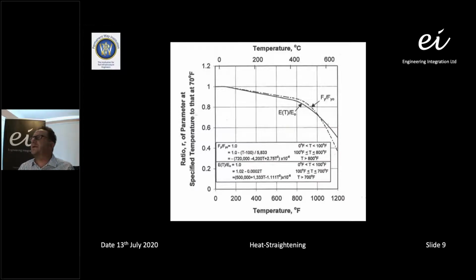This is a typical diagram showing the reduction in permissible stress based on temperature. So obviously we don't want to heat the structure too far, because we reduce the permissible stress significantly. Our target temperature, our critical temperature, is around about 650 degrees C. At that temperature, we are looking at a reduction in permissible stress or yield stress of around about 60%. That's if the whole section was heated up simultaneously. But we're actually applying heat to a very localized point. So we're not heating the whole cross section of the steel girder up simultaneously. We're just doing it at very discrete heat patterns. So that is limited. So the permissible stress is actually a lot higher than what is taken from that chart. So it's the average temperature of the section that we're looking at.